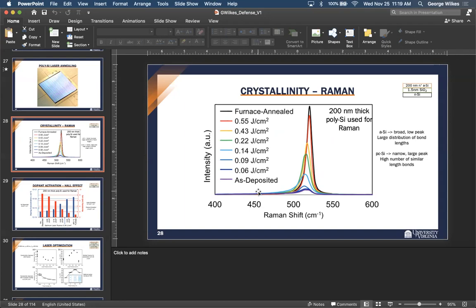That's relatively easy. So why does bond length affect the inelastic scattering? So all of these different bond lengths will have a Raman signal, but this is basically a counting procedure. The intensity is just a counting of the number of bond lengths. So if you have a bunch of them at the same bond length, the Raman signal at that particular Raman shift will be much higher. Are you looking for more fundamental? Yeah, you're right. I just wanted to see if you knew. It's phonons, right? Right. So your phonon frequency will change depending on bond length.